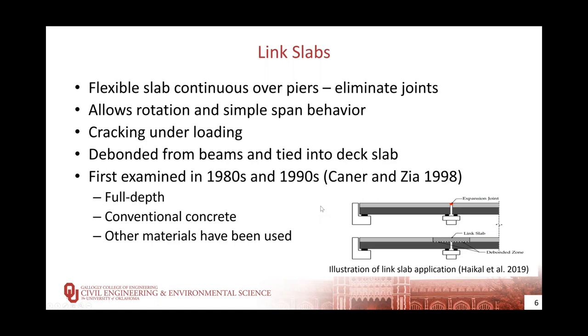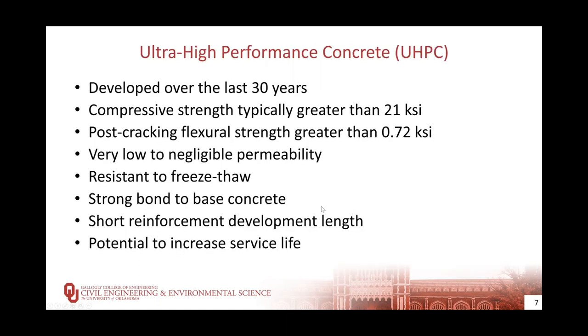UHPC, or ultra-high performance concrete, has been developed over about the last 30 years. It's got a very high compressive strength. If we look at the FHWA definition, 21 to 22 KSI as a minimum. But the more important thing for link slabs is the flexural strength. And with steel fibers included in the UHPC, we get a post-cracking flexural strength that needs to be greater than 0.72 KSI to meet that FHWA definition.